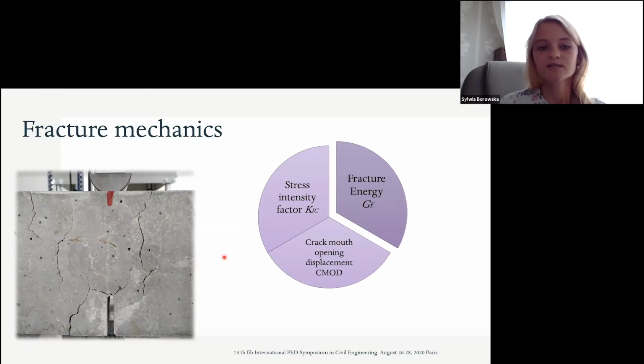High-strength concrete is characterized by a rapid increase in initial strength, which leads to the initiation of numerous places with different characteristics of primary deformation. Insignificant in the initial period of existence of concrete elements, discontinuities may, as a result of destructive environmental impact, lead to the catastrophe of the structure. The connection of fracture mechanics parameters with the degree of damage as a result of cyclic freeze-thaw leads to a more precise description of the integral degradation of high-strength concrete.